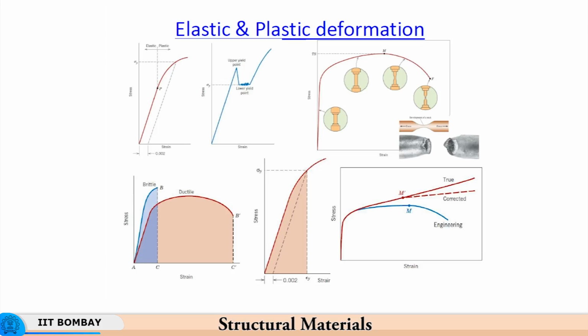because now the work hardening capability of the cross section is lost, and therefore you have deformation taking place at decreasing stress, and you have what is called localization of strain taking place as well, in a cross section where the strain tends to get concentrated. Why? Because now that cross section is not able to get any further work hardened. So, earlier every cross section was supporting the load.